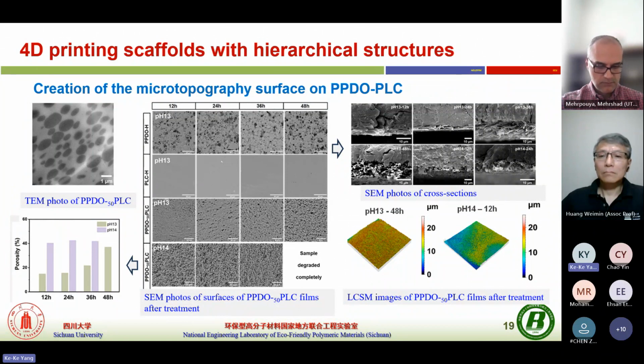We put it in aqueous solutions, and we find the PPDO segment shows a much faster degradation rate, while PLC shows a slower degradation rate. Then in the copolymers, we find the surface can create a micro-scaled porous structure.